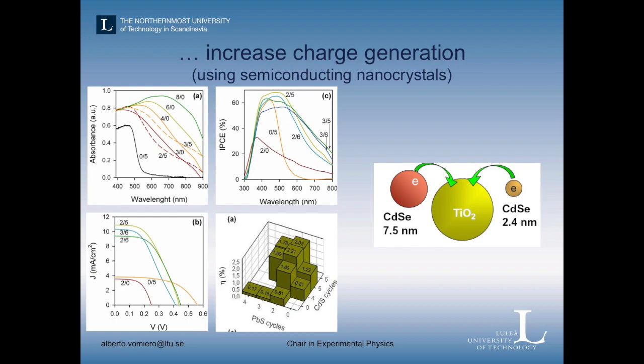And that's pretty critical from this point of view, because you could say, well, I want to use a crystal which absorbs all the sunlight, but if you use that kind of crystal, is not able to inject the charge to the other material. So unfortunately in this field you have to try the best compromise, which is not the best solution for all the processes. So there is no solution in which you can absorb fully the light, don't disperse any energy during transport or injection or collection. And I think this part of the panel in the bottom right gives you an idea how it works. If you see, we have different compositions of these cadmium sulfide, lead sulfide materials, and the best is in the middle. And in the middle, unfortunately, you don't absorb all the light, but you maximize the ability of transforming the sun power to electricity.